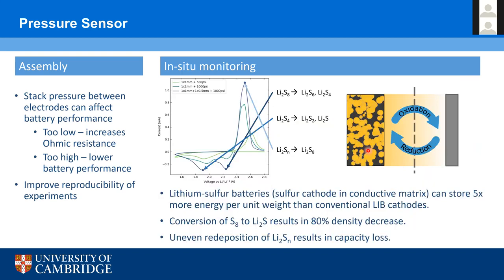Yeah, so a second example that we've looked at is in lithium-sulfur batteries, which are, again, different from conventional lithium-ion batteries that are currently used commercially. They use a sulfur cathode inside a conductive matrix, which is usually made of carbon or some kind of porous conductive material, and they're able to store about 5 times more energy per unit weight than a conventional lithium-ion battery cathode made from metal oxide, such as cobalt oxide. And these store energy through the conversion of elemental sulfur, which is S8, to lithium sulfide through a series of stepwise reactions, which are indicated within the electrochemistry, which you can see on the left here as a series of different voltage peaks.